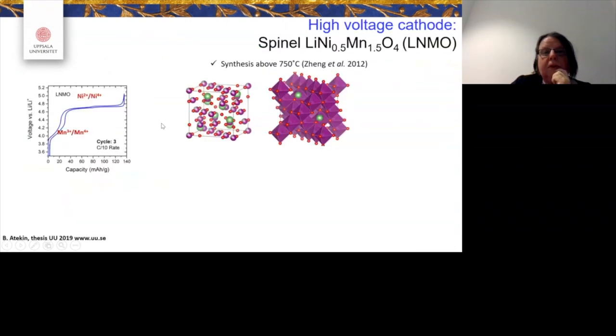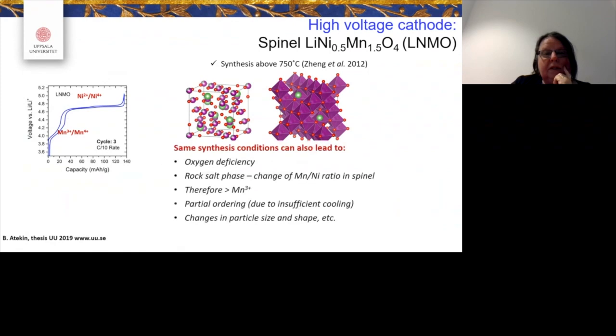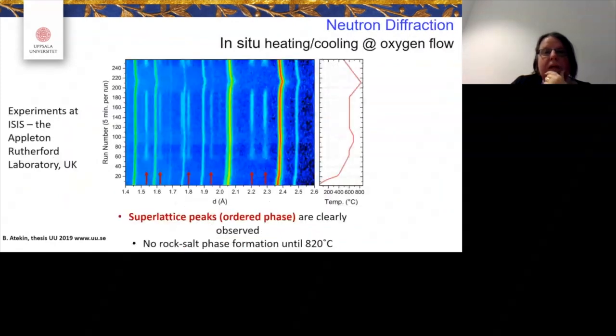So what we did then was that we actually decided to look at a really oxygen full structure, so that we really had the full and not the defect structure. And having this oxygen pressure, we actually did a thermal study using neutron diffraction to really see how that ordered-disordered formation is happening. When is that happening, and what's going on?